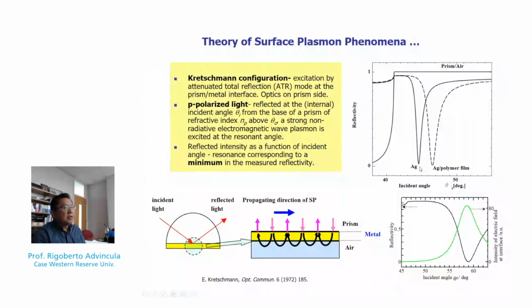So this means that the light is actually being channeled on the surface of the gold film. Now, what happens if you put a polymer film on top of that gold is that this reflectivity curve shifts. As shown here in the dashed line, by adding a polymer layer, that curve or dip shifts to the right, or to a higher angle.